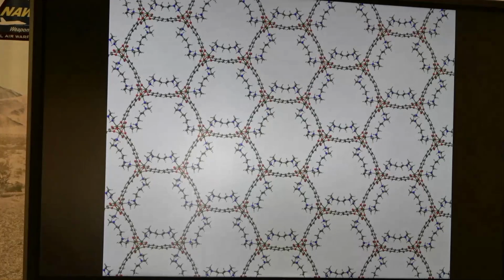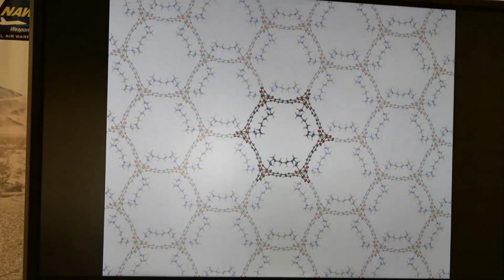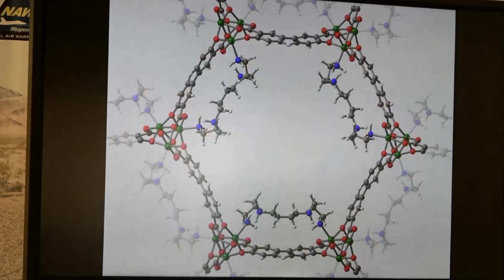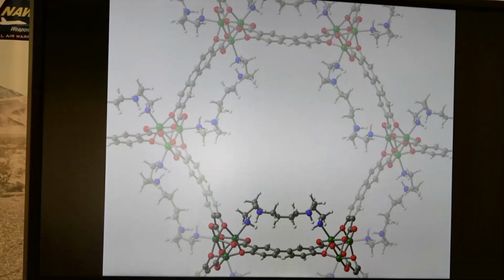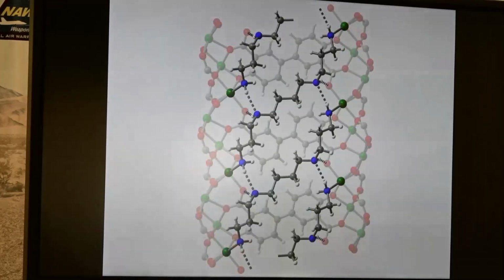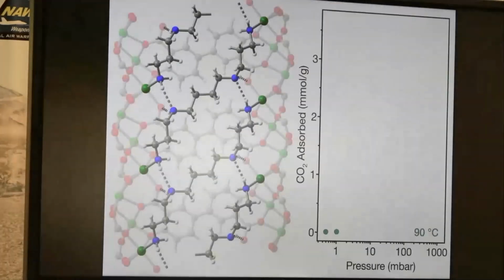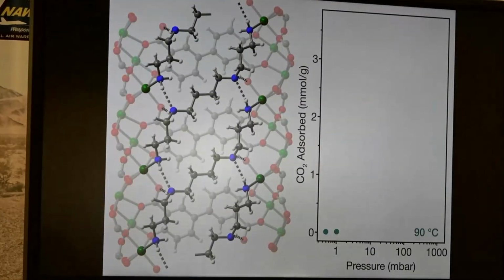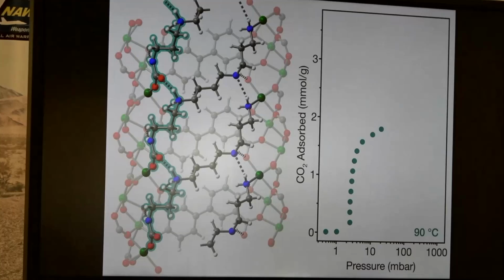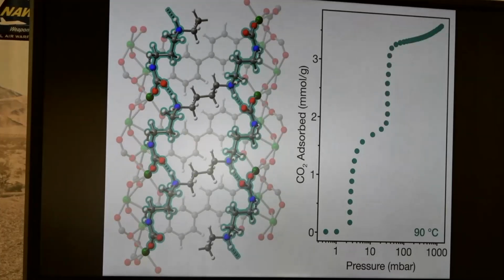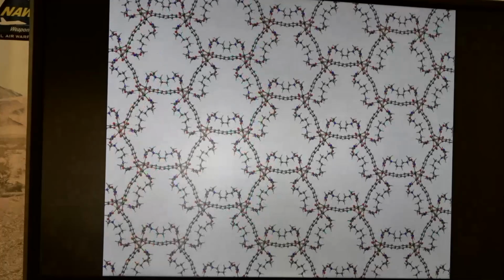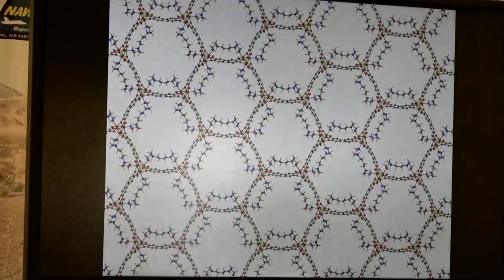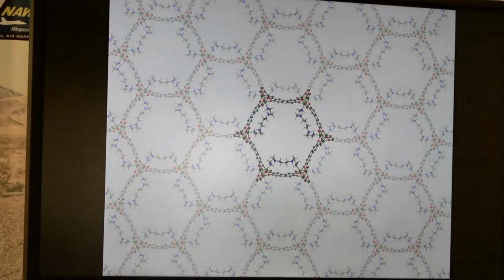So here's a little movie of what's going on in this tetramine MOF. We're going to look down one of the channels in the crystal structure. This is going to rotate 90 degrees, and you'll be looking down on rows of tetramines. And one thing to note is that CO2 is going to adsorb at two slightly different energies at each end of the tetramine rows. And so instead of a single step, we have a double step for CO2 absorption. Once you've loaded with CO2, you can bring in steam, release the CO2, and start again.